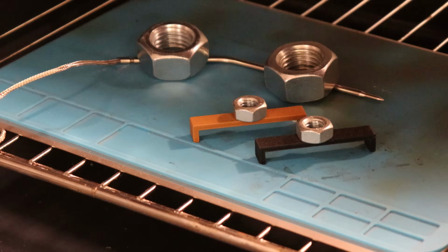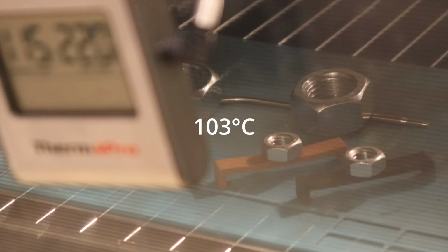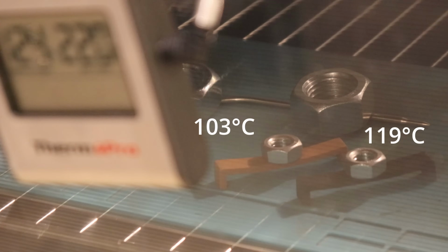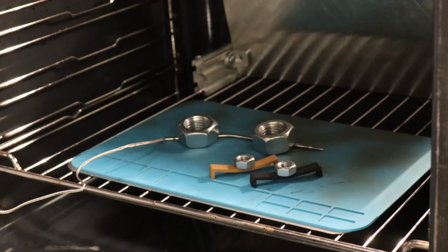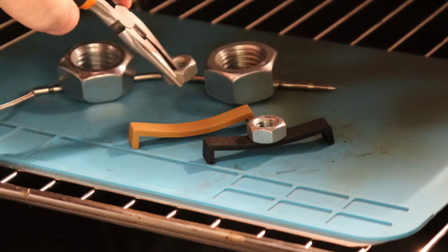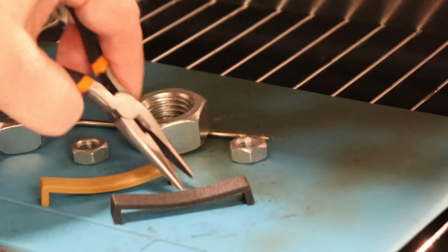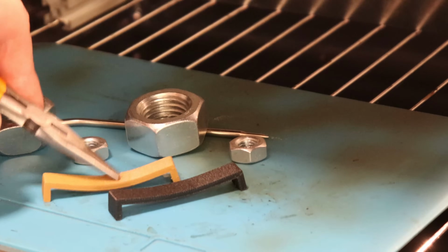The temperature test in the oven: an M10 nut as a small load, and I want to record the temperature of the first deformation. This is a sped up time-lapse video, and the first deformation I noticed on PET-GF at approximately 103 degrees Celsius, and a little bit later on the PET-CF. Then I opened the oven to see how hard or flexible these materials are. And you will see the PET-CF is still quite hard and the PET-GF is soft and flexible.